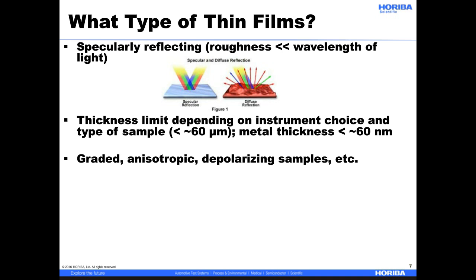So for transparent materials, I'll say around 60 microns is the cap for thickness determination. May be able to go a little bit higher, again based on the instrument that you have. Whereas for metals, we say around 60 nanometers is the thickness cap, because metals are highly absorbing.